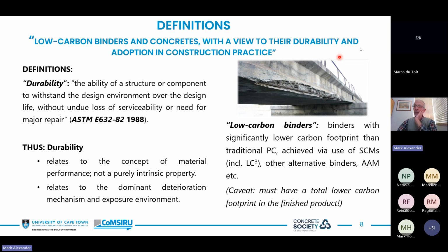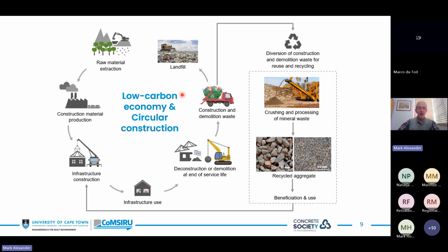On the other hand, if we look at how low carbon binders are defined, I've made up this definition. I think it's not bad. Binders with significantly lower carbon footprint than traditional PC or Portland cement, achieved via use of supplementary cementitious materials, including these calcined clay materials and other alternative binders, and possibly the alkali activated materials, which may have a niche, but quite a limited one. And the caveat here is that any material that we are contemplating here as a low carbon binder must have a total lower carbon footprint in the finished product. It's no good doing that on a limited basis. One has to look at the whole picture before you make your mind up. That's very important.